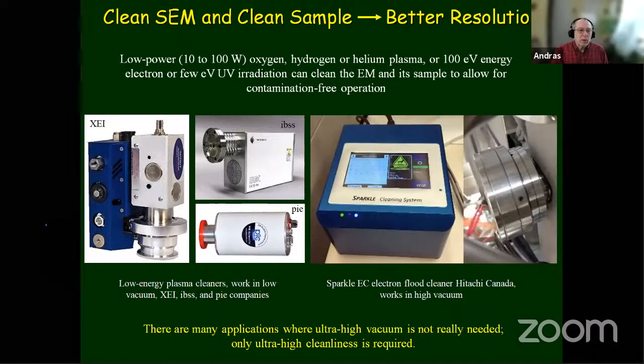So here are some instruments that can be used to clean the microscope. Both TEM and SEM can be cleaned with versions of these. One is plasma, low energy, 10 to 100 watt oxygen, hydrogen, or for even more sensitive samples, helium plasma could be the way. But there is a new one here, which is particularly remarkable.